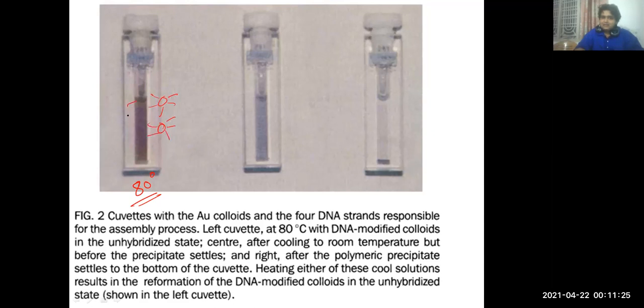And what you see, this red color, is because of the gold nanoparticle which is visible. So 700 nanometer is the absorbance maxima for gold nanoparticles, and that is why this appears red. The moment I reduce the temperature all the way down to 0 degrees, this is actually room temperature, I drop it down to 0 degrees. What I see is there is linker present in the mixture, but the linker does not link. But at 0 degrees Celsius, the linker starts to renaturate. And as a consequence, you have assembly formation.